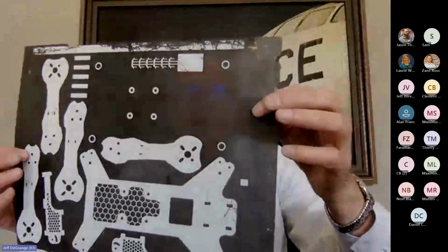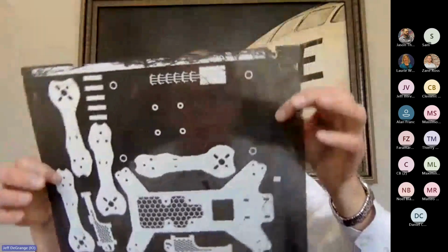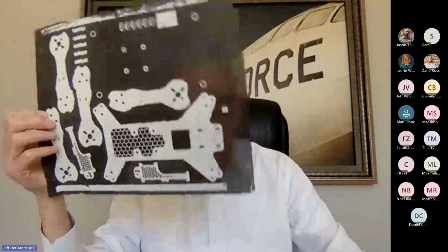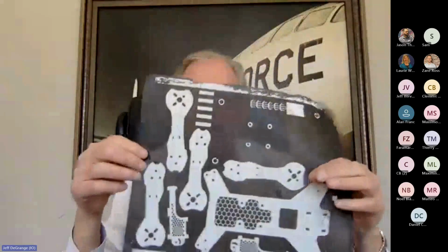On fiber volume content, I'm going to give you a two-part answer. On the non-woven surfacing veils with the random dispersion of fibers, they run in X and Y. And that's where you're getting your strength properties, by the way, everybody. Compared to some of the other additive processes, it's the long fibers where you're getting your strength properties from. On the non-woven fiber substrates, fiber volume content ranges from 20 to 50%. That does not compare to anything structural in the aerospace industry.